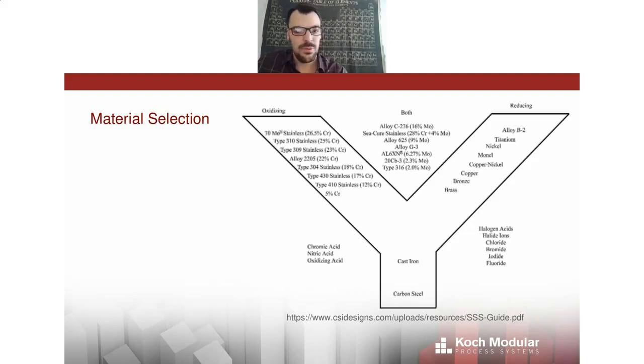And if you have no clue whether you have an oxidizing or non-oxidizing acid corrosion mechanism going on, people choose from the middle of the Y, the metals that are resistant to both. At the bottom of the both-resistant spectrum, we see 316 stainless steel, and at the top, everyone's pretty much heard of Hastelloy C276, sort of the jack of all trades, king of corrosion resistant alloys. So those two metals get chosen a lot. There are very deep and plentiful supply chains for alloy C276 and 316 stainless steel.